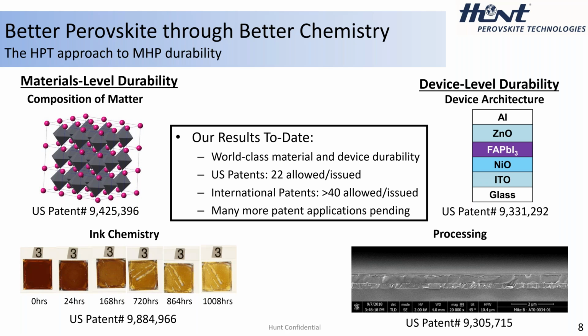The perovskite is a unique material compared to other semiconductors, and so it has unique considerations for its stack. Now, nothing particularly special, just unique. So all solvable problems. In the durability side of materials, we have composition of matter, so the cubic FAPbI3, and ink chemistry, because this is printed, and so you have to have an ink, right? The precursors are dissolved in a solvent, and they have some additives all mixed in. This is printed and then annealed in some form or fashion to make the semiconductor in situ on the substrate surface, similar to what you can see in the lower right-hand corner, a cross-sectional scanning electron microscope image of one of our perovskite materials to highlight processing. If you process well, you can make the perovskite very flat, and then also the architecture. And we have patent protection in all 4 of these core pillar areas.